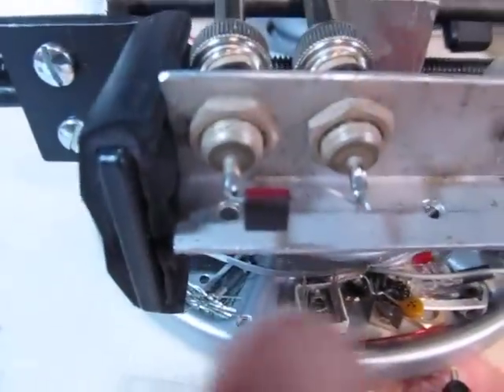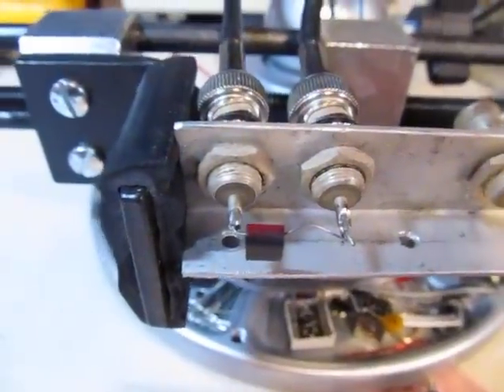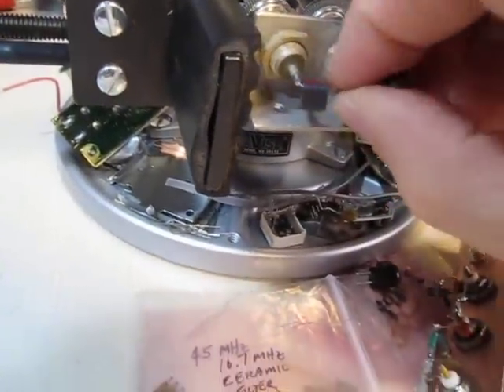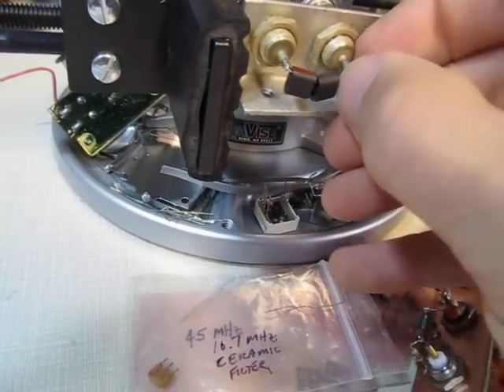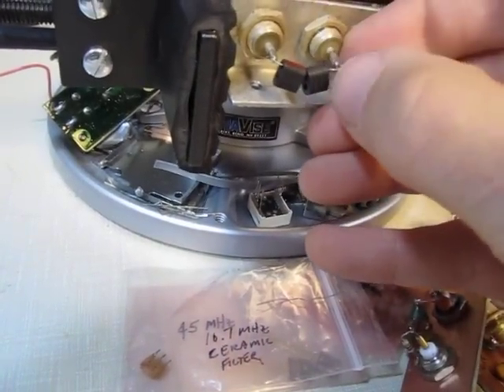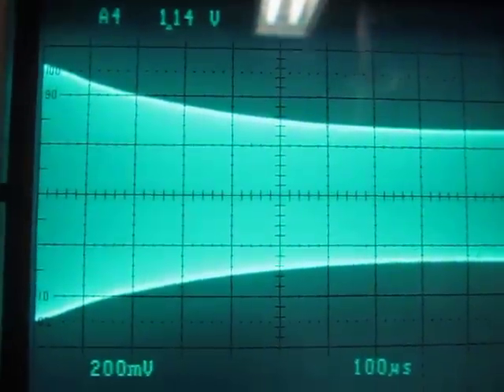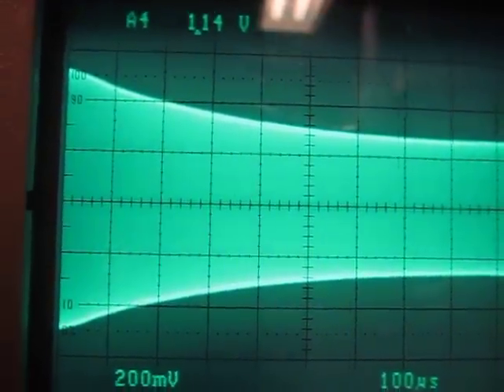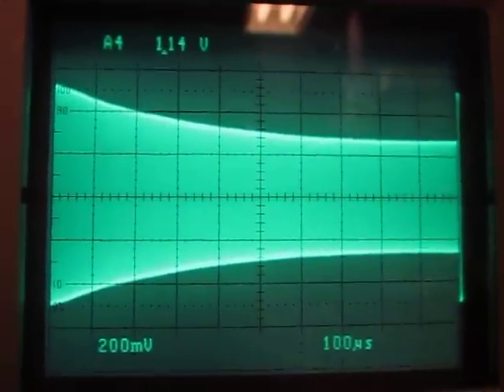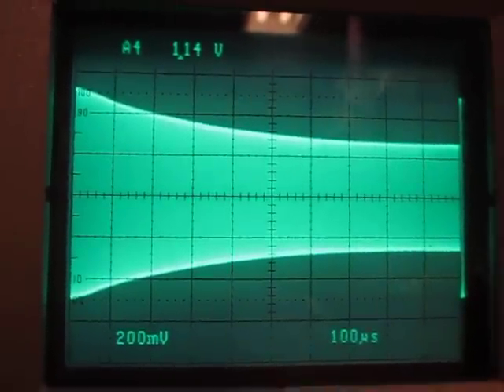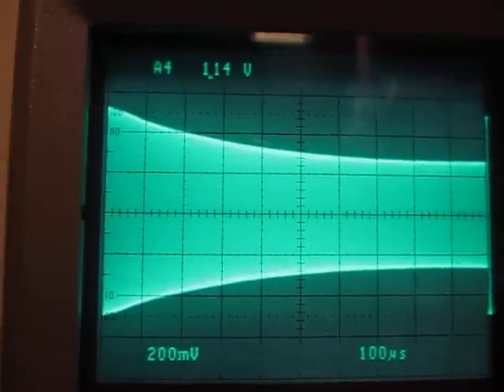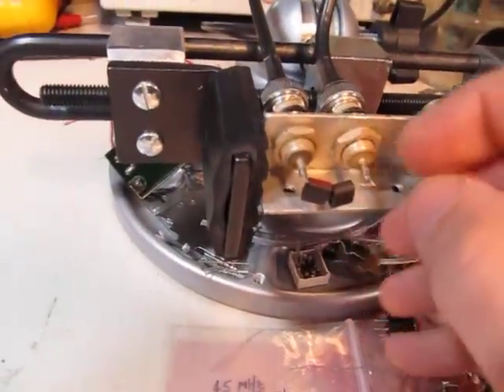That's essentially a series resistor at those frequencies. If you add more cores it just gets better. I'll open this up and throw another core on here. Now looking at the scope, by the time I get to the middle of the screen — about 20 megahertz — I'm down about half the signal amplitude, which is less than half the power, about 6 dB down. Just by slipping some ferrite cores on there.